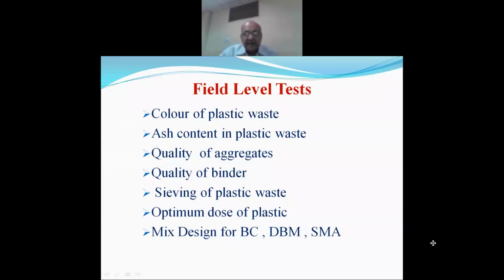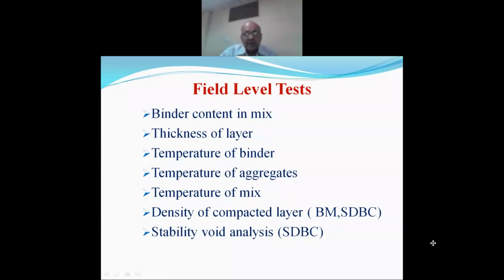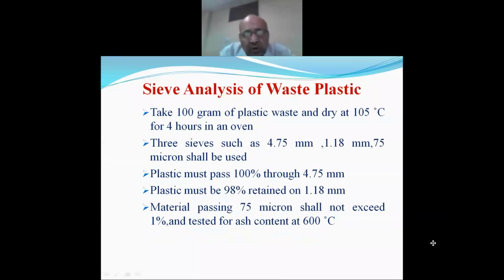Sieve analysis test and ash content at site, besides binder content and stripping test. Size of the plastic shall be again 4.75 to 1.18 mm and ash content shall not exceed 1%. Clause number 900, that is the tests and test frequencies applicable to conventional construction, are also applicable to construction of various specifications of plastic waste modified mixes.